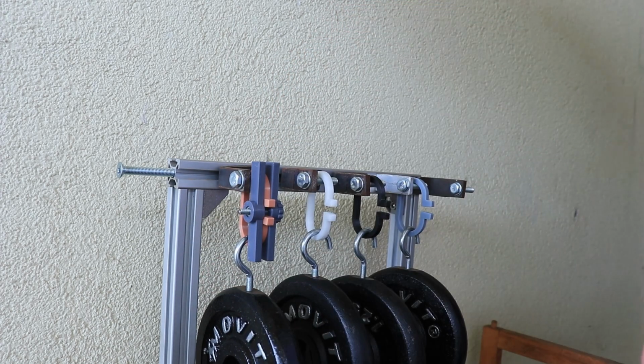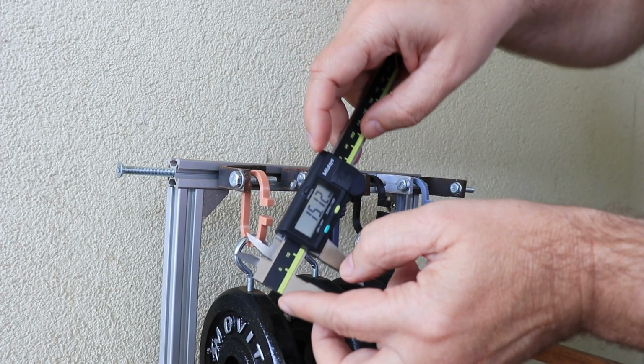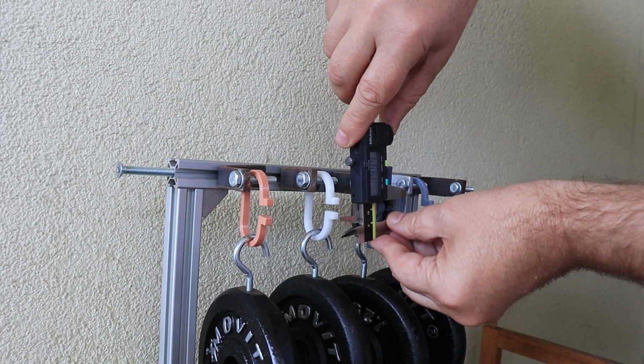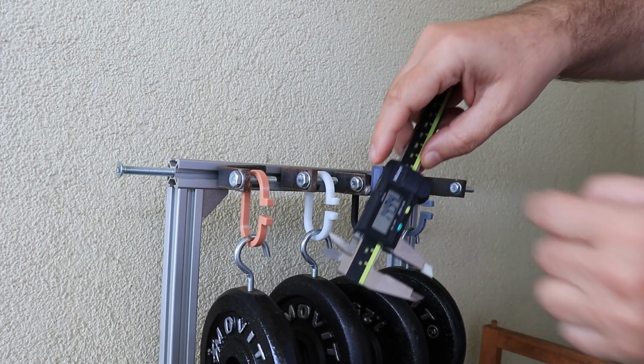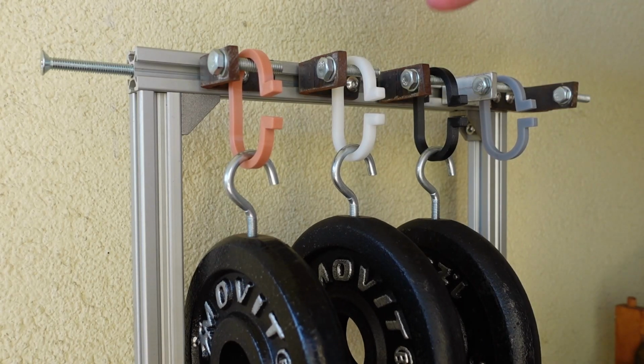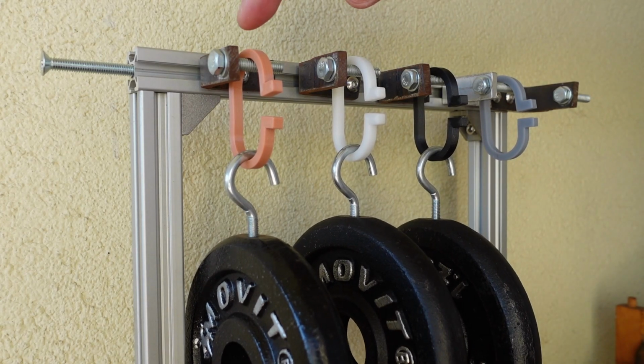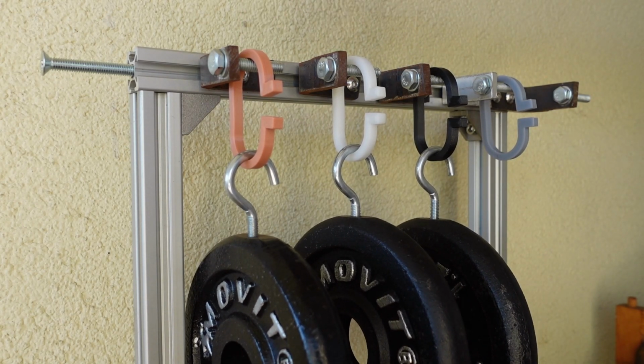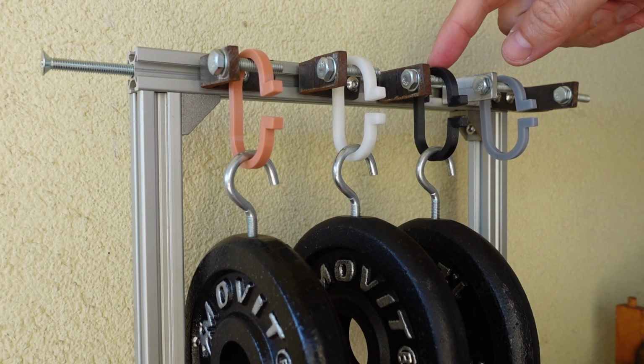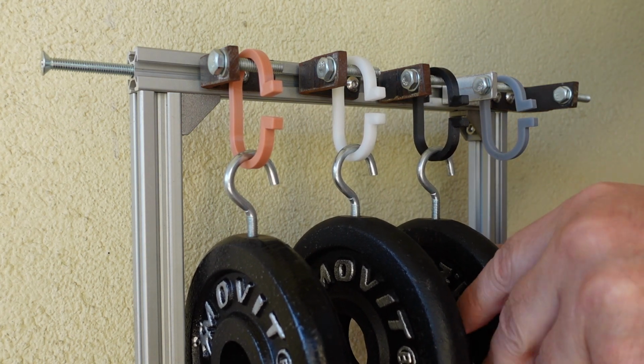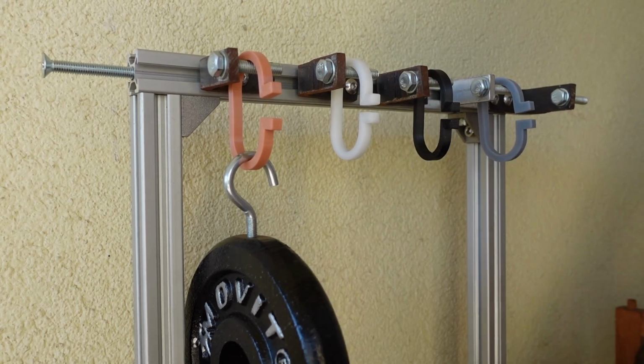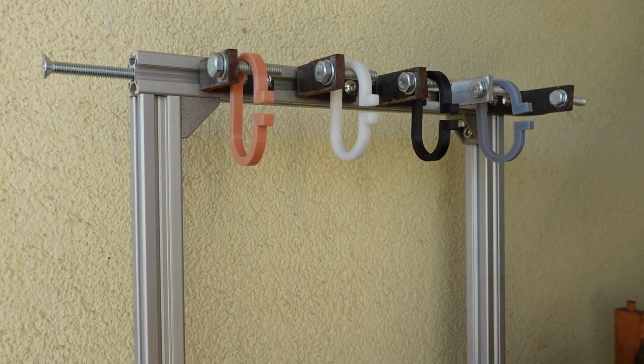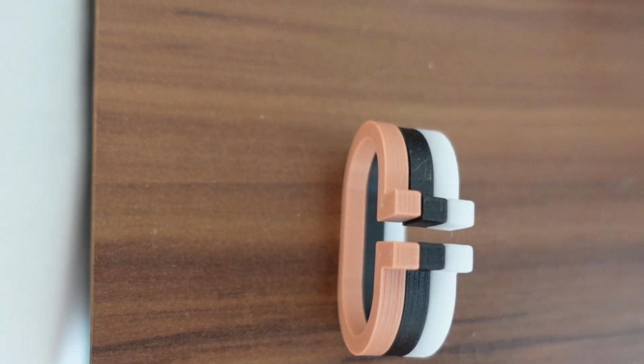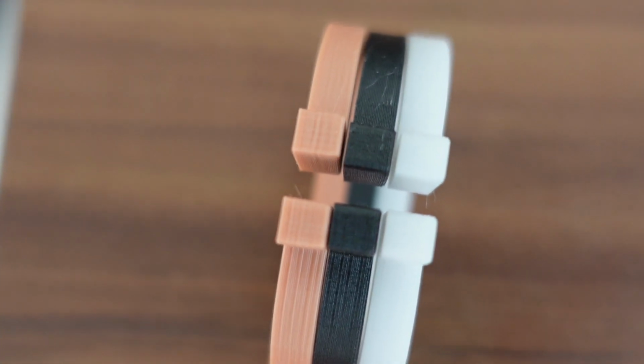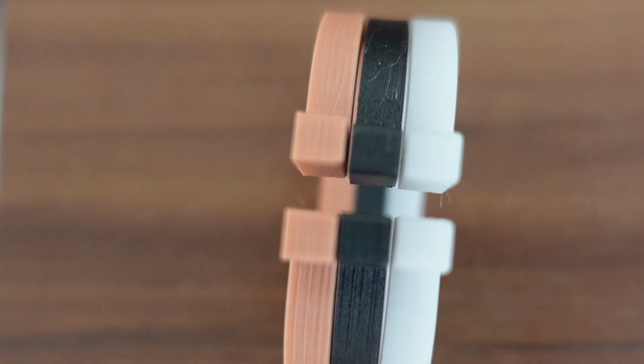1606, 1512, 1494. This is day 6, I already measured them. The biggest deformation we can see on the regular PETG and the smallest on the carbon fiber version. And now let's remove the load. The exact numbers I will show you in the results part. Now it looks like this is the permanent deformation, and what is interesting is that the smallest is on the V0, and of course the biggest is on regular PETG.